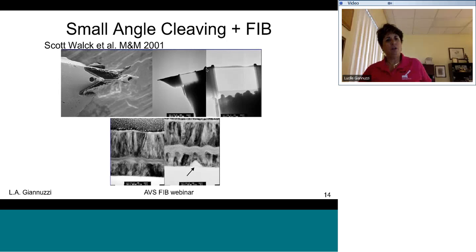All right. Combining polishing and cleaving for FIB is also another way to just get the sample thin enough so that you can put it in a FIB to directly FIB mill on the sample. So with cleaving, you basically are left with a point at the end of the sample such that the thin area, or the area at the end of the point, is really electron transparent. By incorporating the FIB on top of it, you can make a FIB section. So there's a low magnification bright field TEM image, and you can see very easily where the FIB section is being prepared to look at these thin layers.